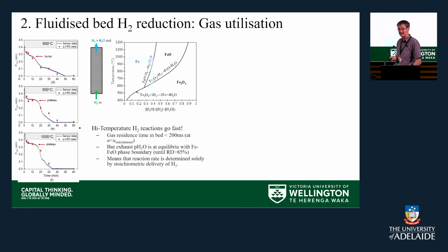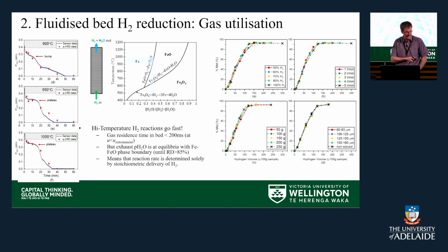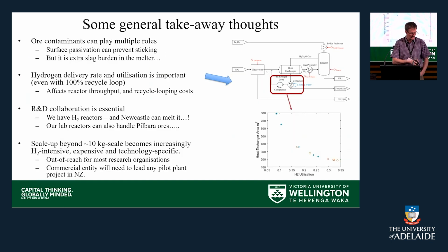Again, showing you just that this is a very rapid reaction. And that has ramifications for downstream design. It also means that actually our reaction rate isn't kinetically limited at all. It's just limited by how much hydrogen we throw in this regime. And so it doesn't matter whether you're going at different concentrations of hydrogen, different particle sizes, different bed masses, whatever, you get the same answer. It's just stoichiometrically sitting at this boundary here until you put enough hydrogen in to do the reaction, which makes some of the modelling fairly easy.